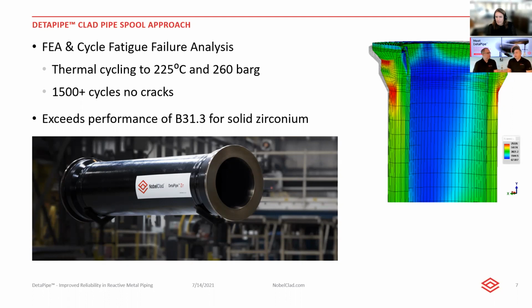What can it do? Well, the only other clad solution out there is loose lining, in some ways. Loose lining does not bode well for thermal cycle and fatigue failure modes. So the first thing we did was we tested our pipe at 225 degrees C and up to 260 bar.